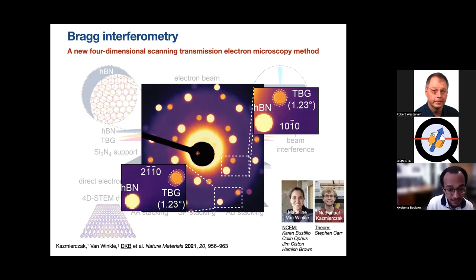So instead, what my really ingenious students, Maddie and Nathaniel, did was they actually found a way of leveraging the very fact that these disks were overlapping to do an interferometry experiment. So they came up with this Bragg interferometry method to analyze and extract quantitative information. I should point out that because we offset the hexagonal boron nitride capping layers from the graphene, they don't play into our analysis. And so we can do all analysis by selecting only what's going on the graphene layers. And this is really, really convenient as a benefit of using the diffraction approach.